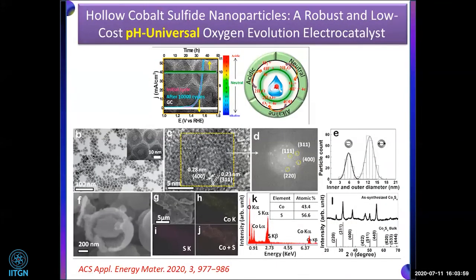After that, we followed this material, and we have now prepared hollow cobalt sulfide nanoparticles. And what is the beauty of this material? It is a robust and low cost pH universal oxygen evolution catalyst. It gives us oxygen evolution in acidic, neutral, and alkaline media. So this is the characterization. I don't want to go through the characterization, everybody knows about that. We can just see this is the hollow nanoparticle. You can see a hole there, and this is because of the galvanic replacement.